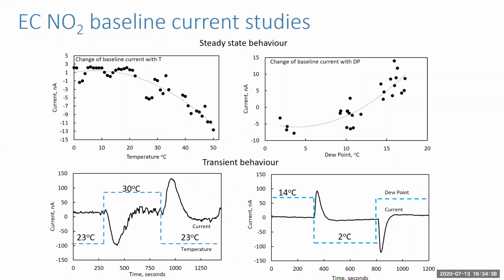What we have been able to do is to replicate those temperature and dew point behaviours in the laboratory. And in the top two graphs here, we have a graph on the left-hand side showing the baseline current in response to steady state temperature changes, and on the right-hand side, dew point changes. So these graphs are made by changing the temperature, waiting for the whole system to stabilize, and then measuring the baseline current. And you can see that there is a response to temperature changes and to dew point changes. And these effects are on the order of a few nanoamps above the baseline current.